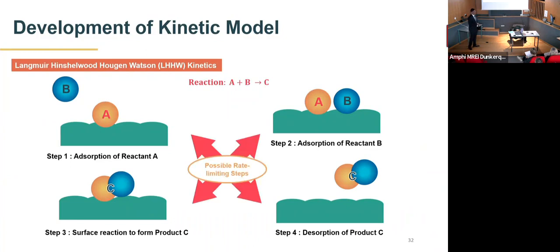And in step 4, we have the desorption of this product molecule C. All of these steps, that is the adsorption, surface reaction, and desorption steps, could be a rate limiting step, and therefore can govern the reaction rate equation and therefore the rate of our reaction.